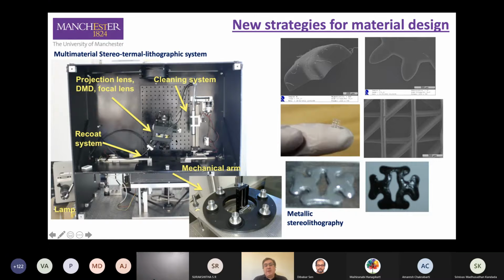And then we use optical fibers to irradiate a digital micromirror device shown here. In fact, the machine has two DMDs. This image only shows one DMD. And then the image created in the DMD is transferred and projected on the VAT through a reduction lens. So this lens reduces the image created on the DMD 10 times. So if we consider that each small mirror of the DMD is 40 micrometers by 40 micrometers, we can create an image on the surface of the resin with 4 micrometers of size.